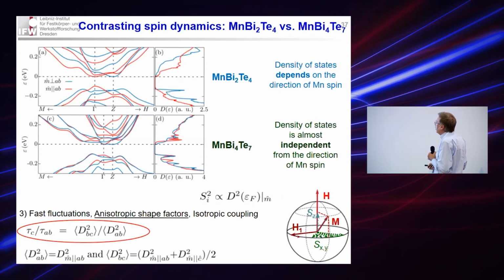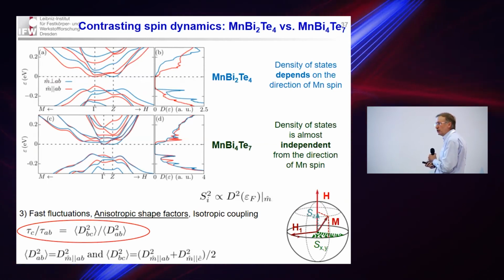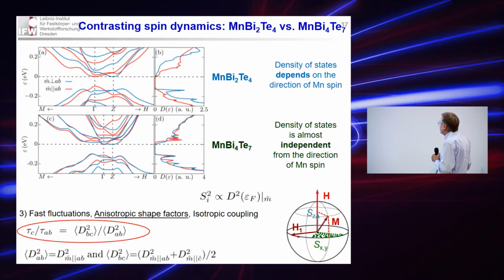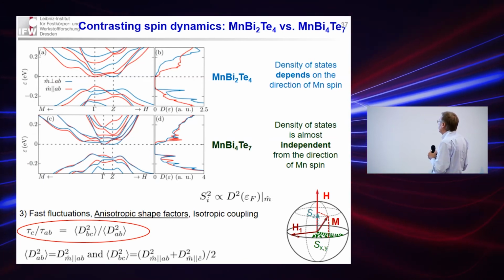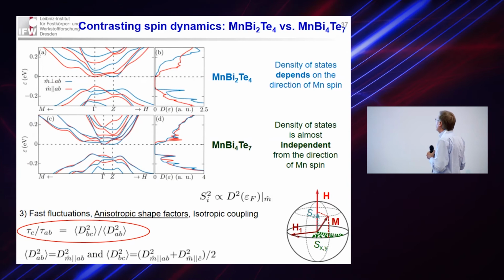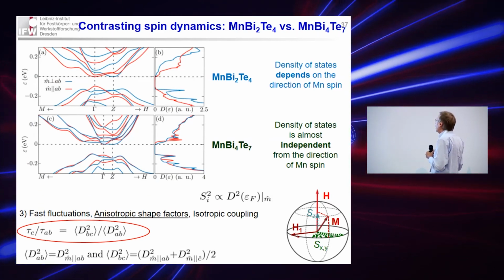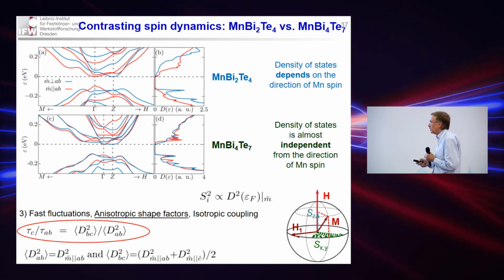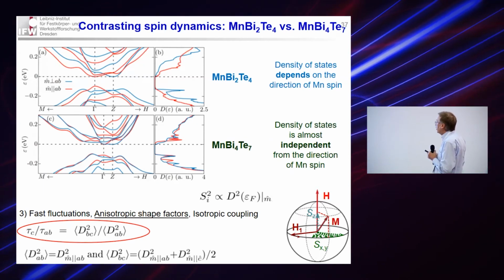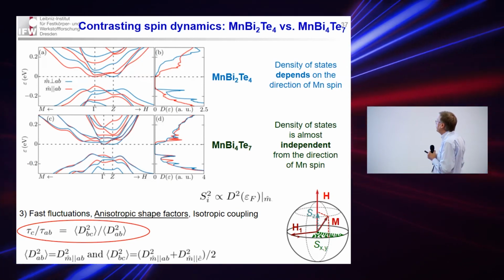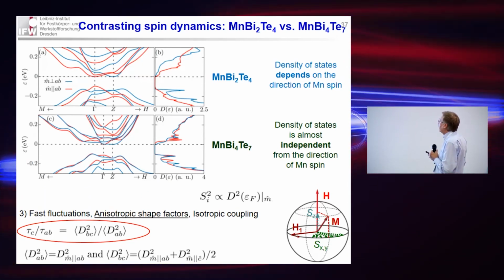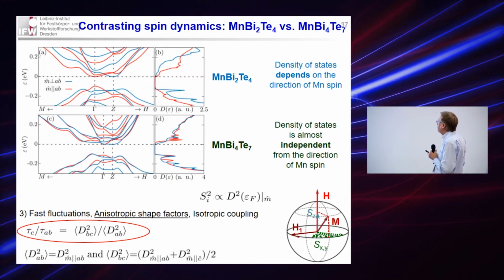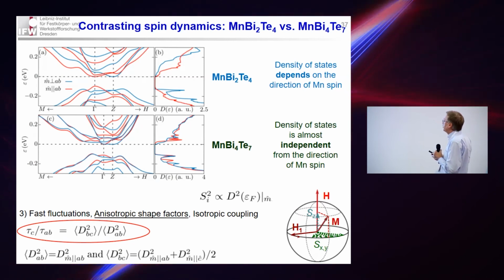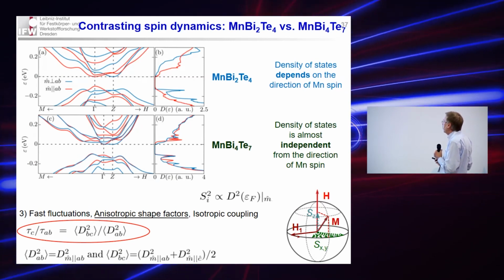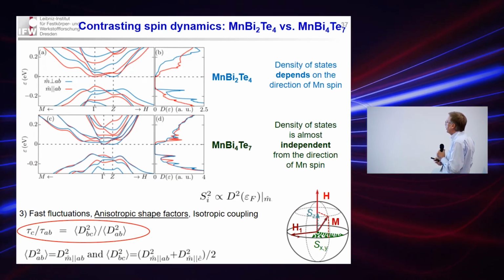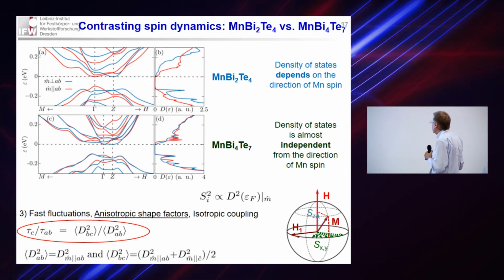Now, to understand why in one case we have a very anisotropic behavior and the other one is not, the theory helped us a lot. There was a band structure calculation where our theory colleagues calculated the band structure with respect to the direction of the localized manganese spins. And here a very interesting result was observed. For instance, this is an integrated density of states for out-of-plane and in-plane orientation of the manganese spin, and one sees a substantial difference in the 1 to 4 materials, whereas in the 1 to 7 materials there's practically no difference, no dependence on the manganese spin direction.